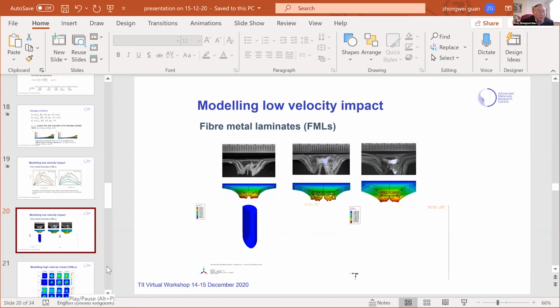I think titanium has much higher stiffness, of course, but it's relatively brittle. That's why the perforation energy is not as high as aluminium-based fiber metal laminates. But if you use, for example, Kevlar prepregs or even Dyneema, the situation will change significantly, because that is a much stronger composite, and the one we use is just glass fiber prepregs. So the strength difference between titanium and the glass fiber is quite large. For fiber metal laminates, ideally you have better compatibility. That will be better. Okay.